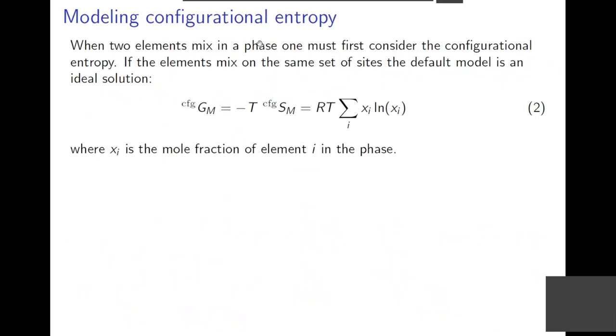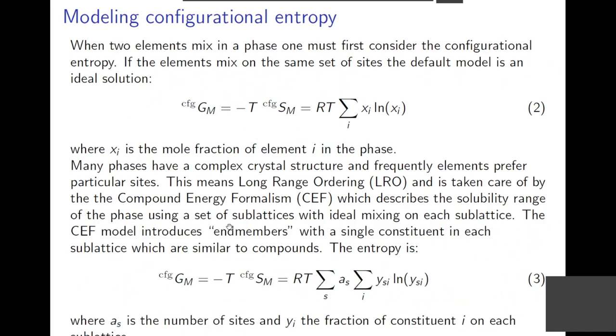Okay, so that is the pure element part, which is a basic part of the CalPhad method. Then you go to mixing, and then you have, of course, the entropy of mixing, which is in a simple phase with just random mixing in the same set of sites. There has been the development of modeling for crystalline phases, where you can include description on the different sublattices. So in this case, with the compound energy formalism, you assume random mixing on each sublattice separately. And that works very well for intermetallic phases and for long-range ordering. It doesn't include short-range ordering.